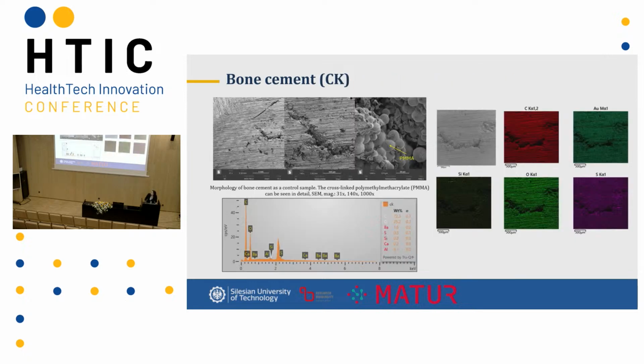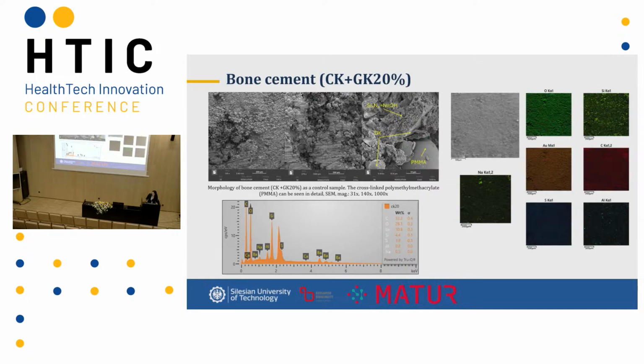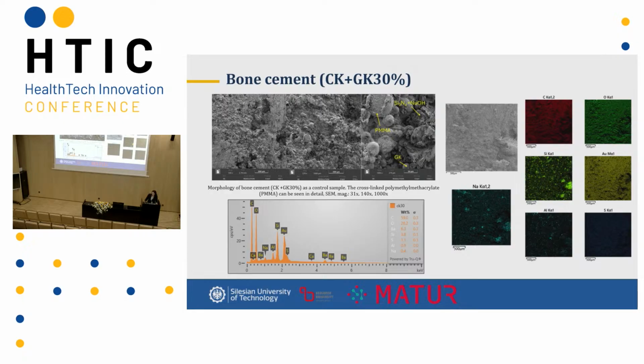I also checked using scanning electron microscopy to see how the morphology is changing and how much silicon appears on the surface. First, it's without filler. This is only PMMA. Here we see the particles of PMMA. Here we have a 20% amount of aluminosilicates. Here silicon appears. This is after modification. We see this on all the surface, and this is the amount of 30%.